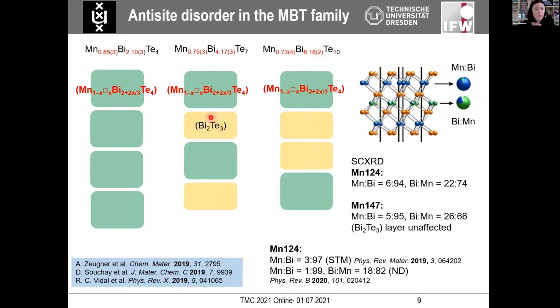Furthermore, in all the compounds of this type that we obtained with bismuth telluride layers in between, some degree of disorder was also present. So here you can see some ratios that we obtained for our phases from the X-ray diffractometry. There were also reports by other groups, from neutron powder data as well as from STM, that 1-2-4 phase is indeed slightly disordered. Back then, when it came to 1-2-4 compounds, this was not considered detrimental, so it was close enough to the idealized composition, and the theoretical predictions on the idealized composition would also hold true for what was observed in magnetometry and partially in surface spectroscopy.